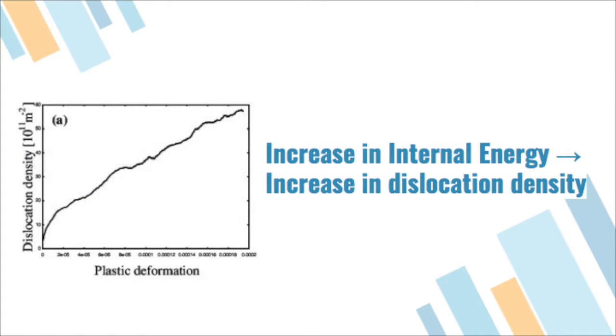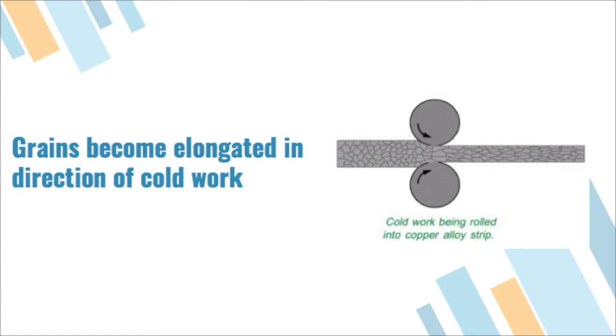On a microstructural level, this increase in internal energy from plastic deformation is associated with an increase in the dislocation density, as well as the density of point defects such as vacancies and interstitials. Now, as we can see in this rolling diagram, the grains become elongated in the direction of cold working and heavily distorted. This distortion is evident from a bending of annealing twins.